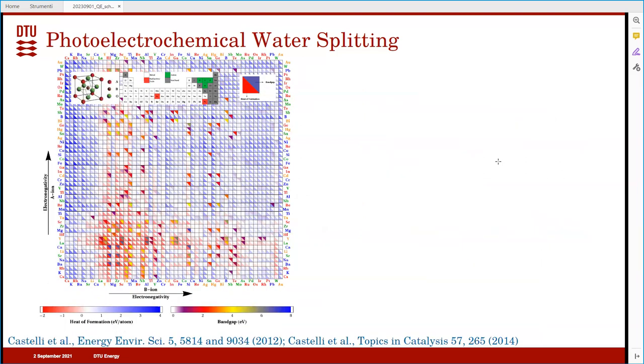So what I did was taking a perovskite and decorating it with about 50 elements from the periodic table in the A and B positions. You end up with a table like this, where you have about 2,500 candidates. The lower triangle is the stability. The upper triangle is the band gap, that is a descriptor for the efficiency of a solar cell.